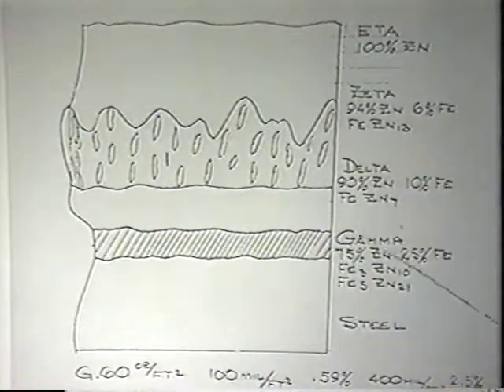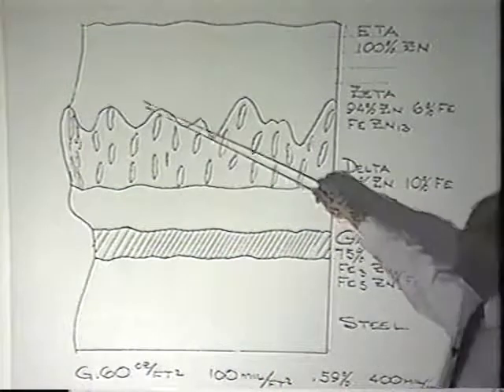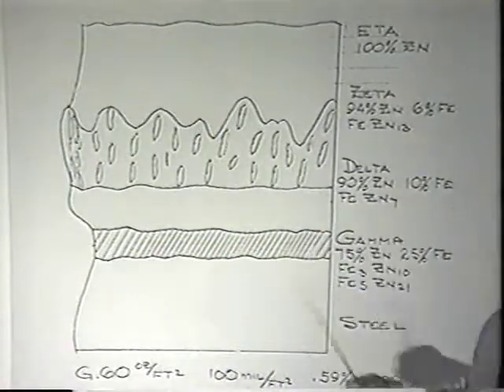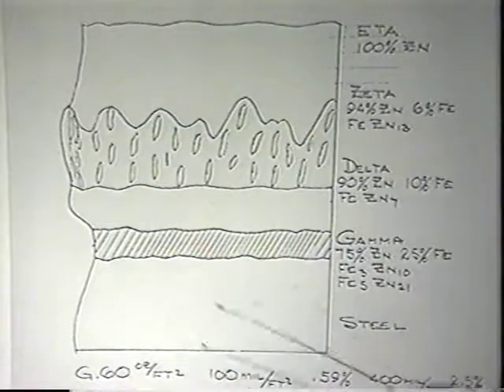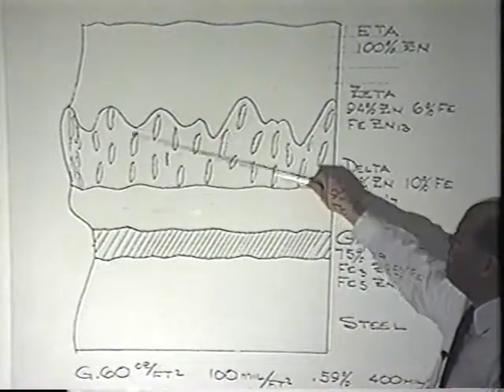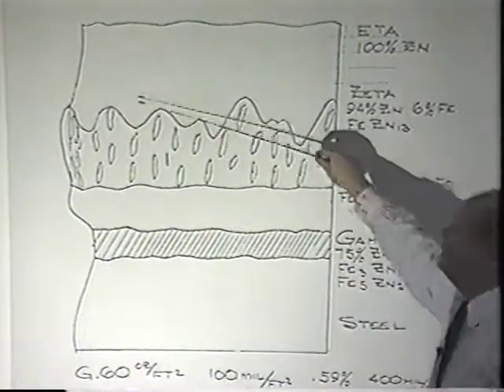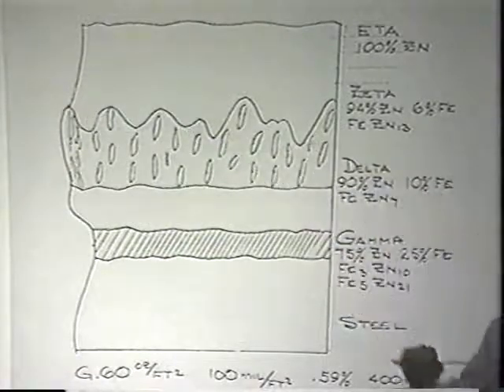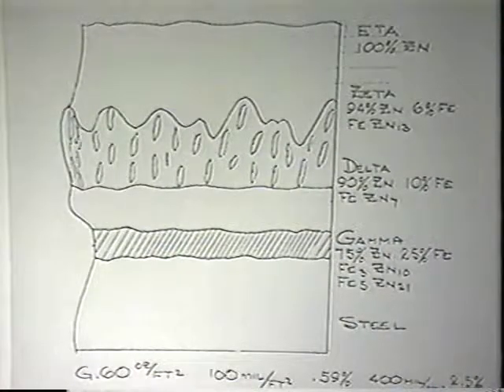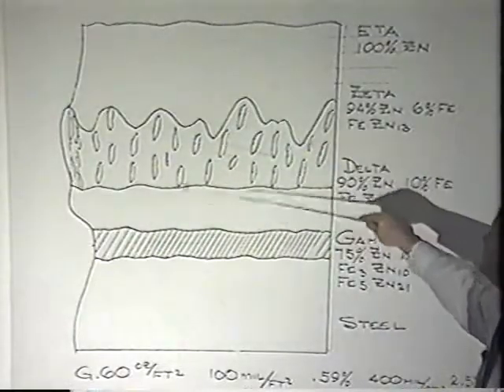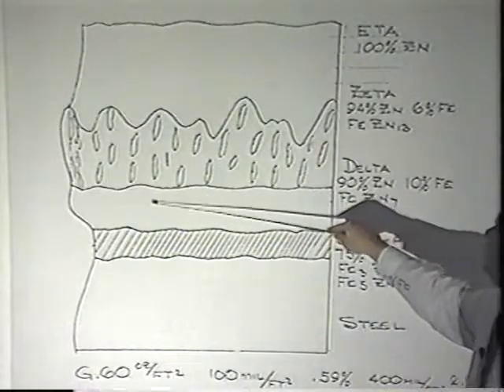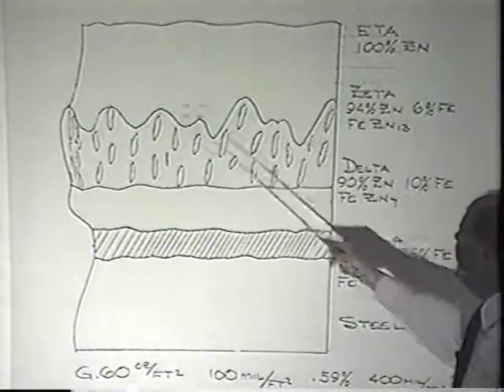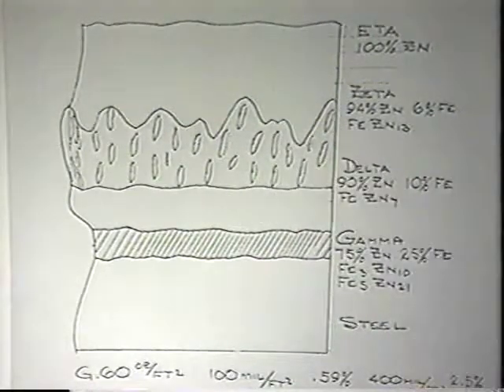So that's kind of how the zinc is held on, as opposed to electrogalvanized, where it's an electrolytic process. You're kind of just dumping it one on top of the other, and the iron that comes through kind of helps hold it a little bit. So you have this zinc iron alloy here, but the important part about galvanized is that you still have pure zinc on the surface. That's why you still have that nice shiny zinc surface to it. This is important to know just as far as adhesion, what's going on underneath the coating. But this is in hot dip galvanized. This is the part that you're interested in.